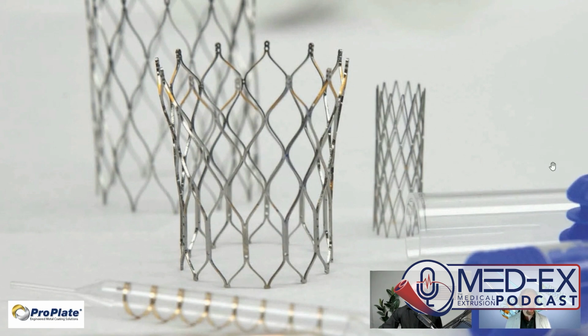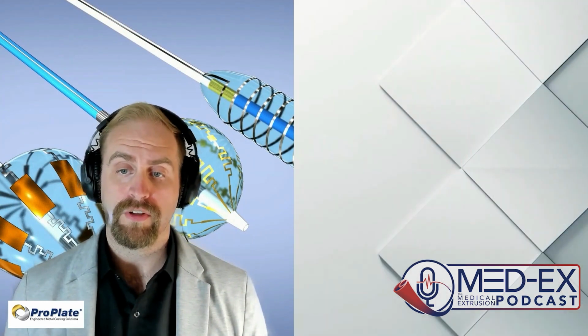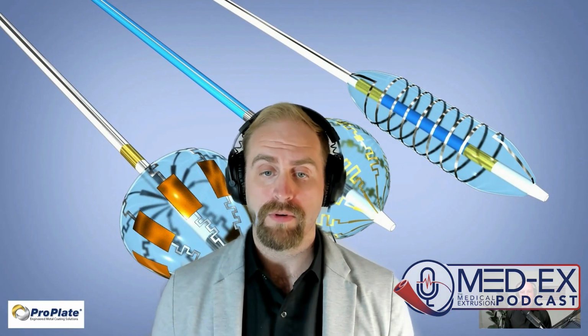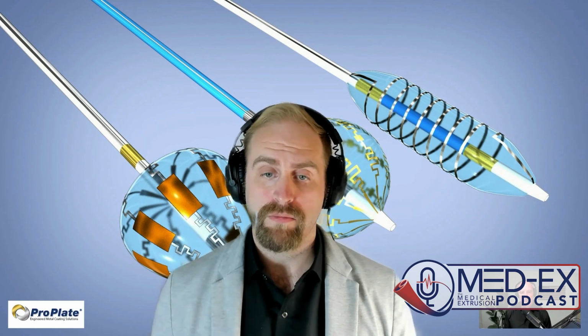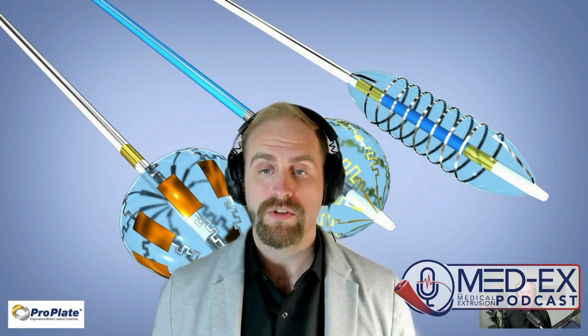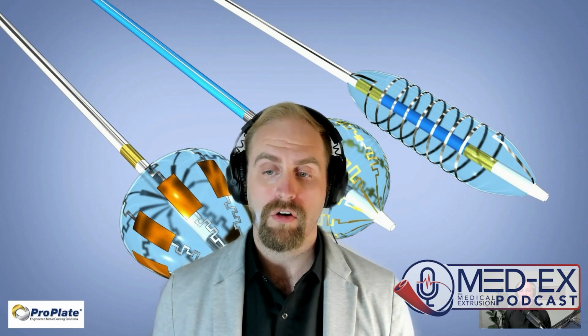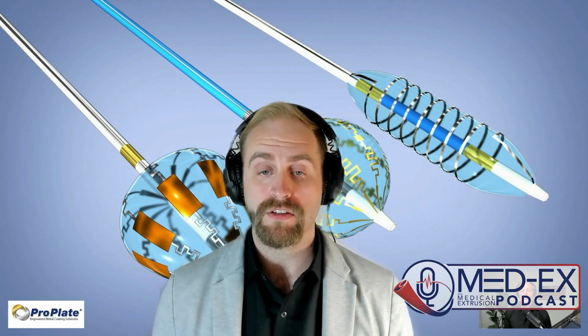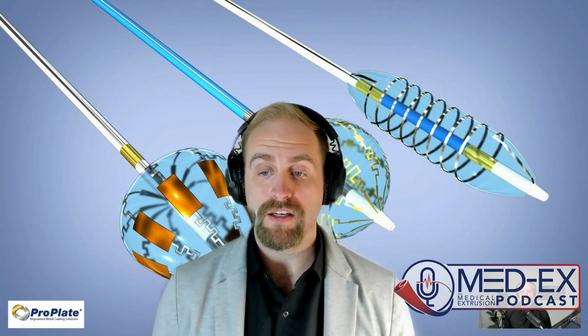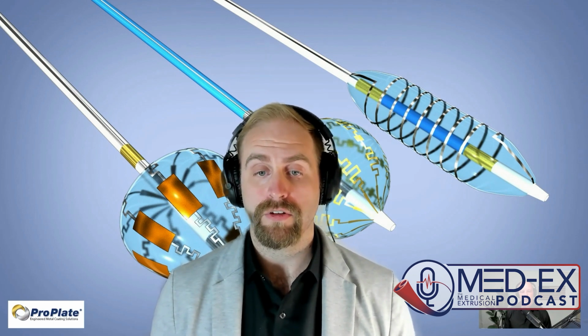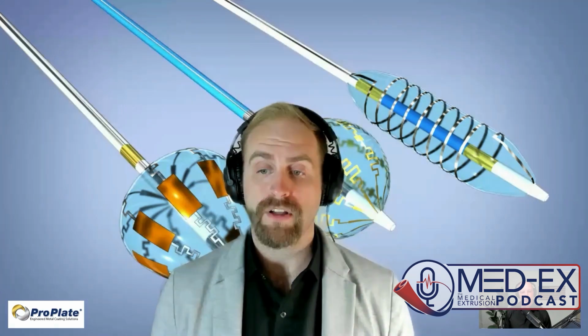Gotcha. There's actually an intention behind that. With these, especially nitinol, but these stent-like structures, whether it be a heart frame or even a neuro stent, when you make a circumferential band around that structure on the strut, you absorb a lot of those shape memory properties or mechanical properties. And so with our coating process, it allows us to just coat or plate the OD only, or even in some cases the OD and the side struts, but avoid the ID of any plating. And this can be an advantage for the shape memory properties and flexibility, like I mentioned.